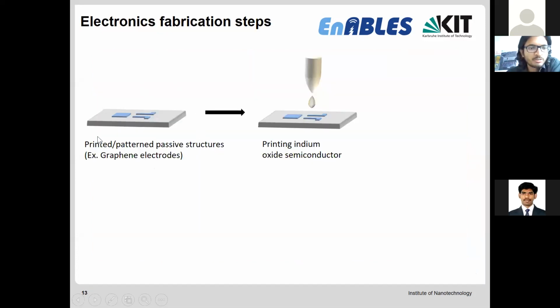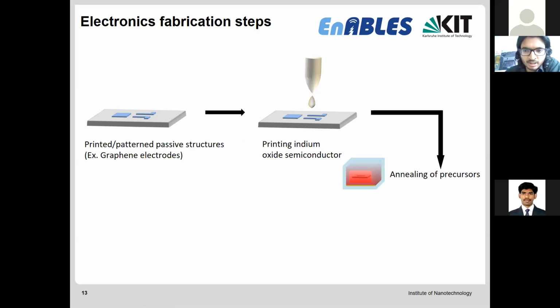So now that we have printed these graphene electrodes using the microplotter and also the aqueous indium oxide semiconductor using the inkjet printer, the next thing would be to process them. For this, we can either heat the precursor. The precursor is nothing but a salt solution that we used to make the indium oxide. Or we can also photo anneal or laser anneal them. This is ultrafast, that's why I call it rapid. This happens in a few milliseconds.